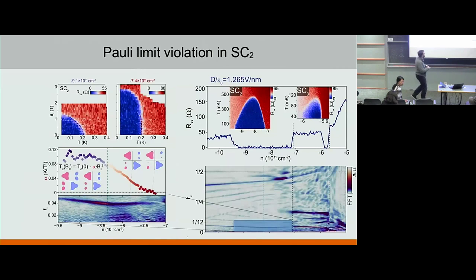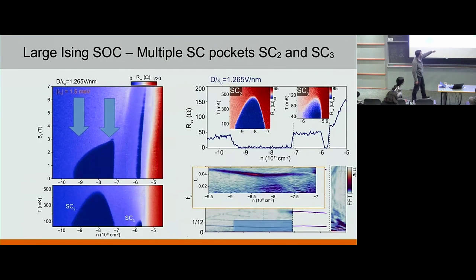So essentially, here's the data. It's kind of growing, but not too much. It's relatively growing if you go to lower hole doping. But the main point is that a lot of the change is absorbed by this smaller pocket, because this small pocket doesn't shrink anymore, or relatively. So you can kind of theorize why this could happen with some in-plane field and things like that.